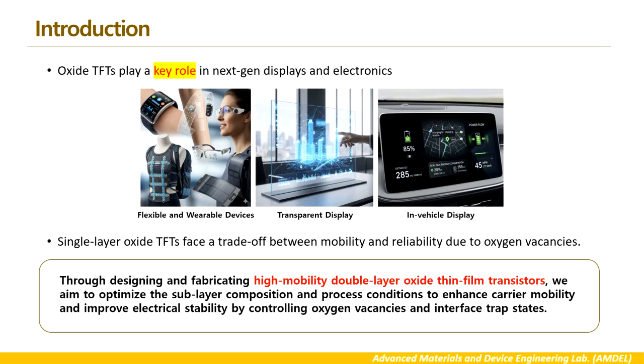In this research, our goal was to design and fabricate double-layer oxide TFTs that achieve both high mobility and electrical stability. We focused on optimizing the sub-layer composition and process conditions. By carefully controlling oxygen vacancies and interface trap states, we aimed to overcome the traditional trade-off between mobility and reliability.